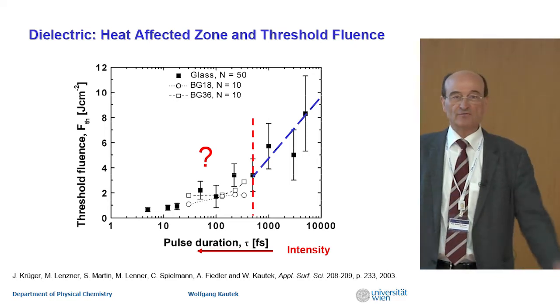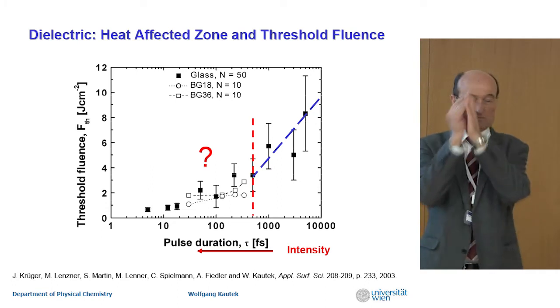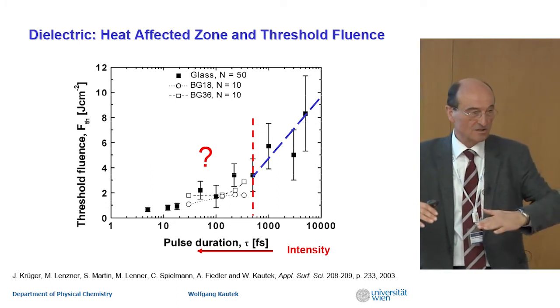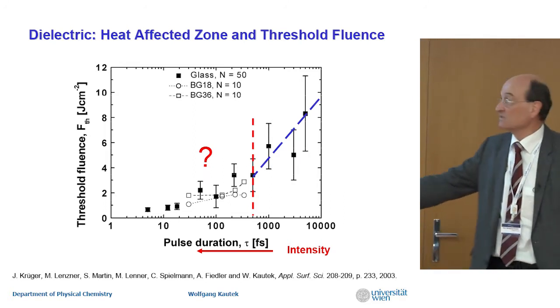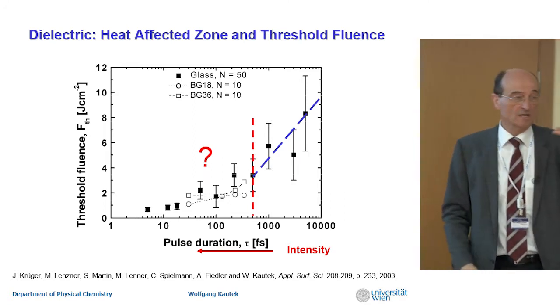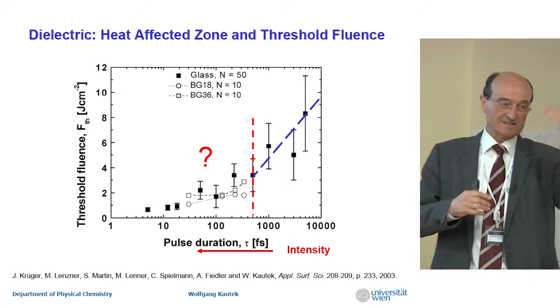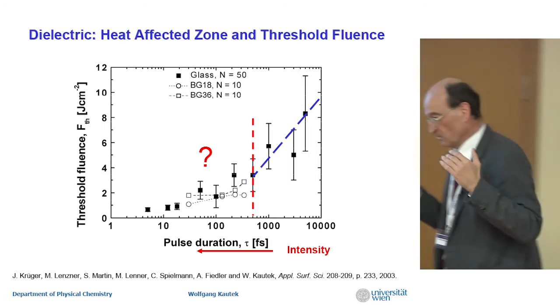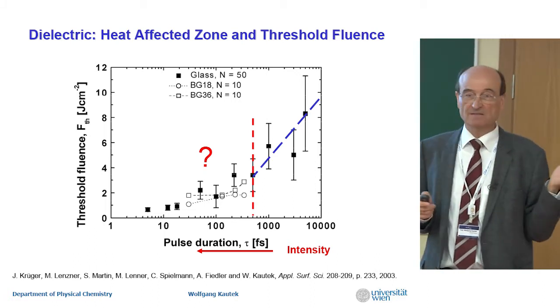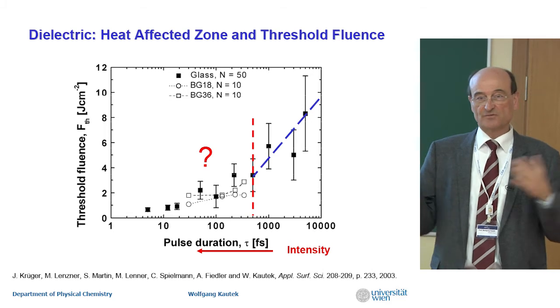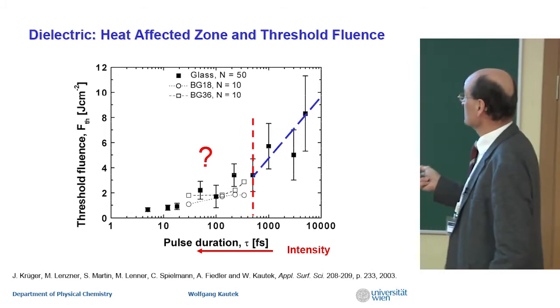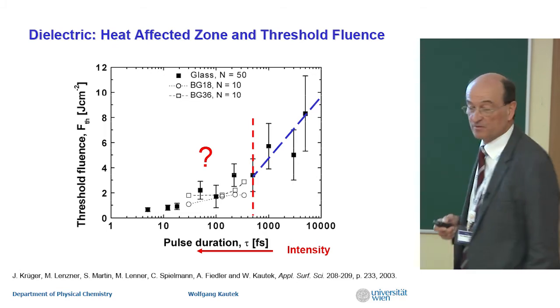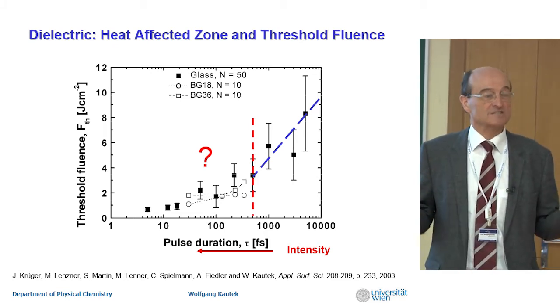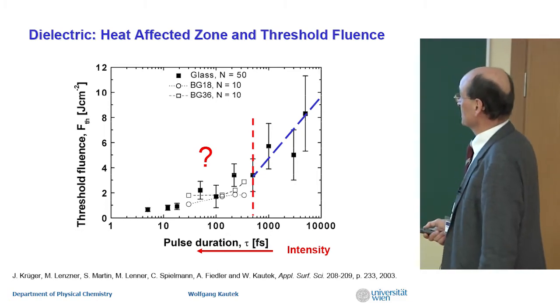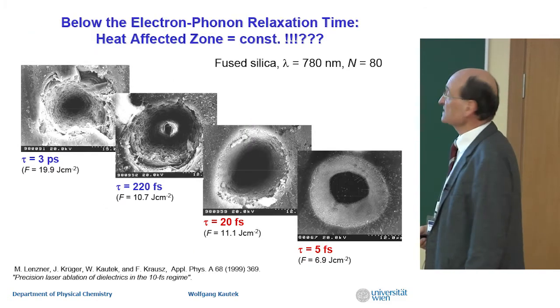Why? Because the heat is dissipating, yeah, and therefore you're losing the energy for evaporation. So at longer pulses, the intensity is low, so you're losing the energy into the bulk of the material. And that goes all the way down to the time where the electron phonon relaxation time takes place. Well, and below that, nothing should happen, because then the material just gets hot after the electron phonon relaxation time. But what we observed, we still had a reduction of the threshold fluence. And that we didn't understand at that time. And then we did another experiment. We looked at the quality.